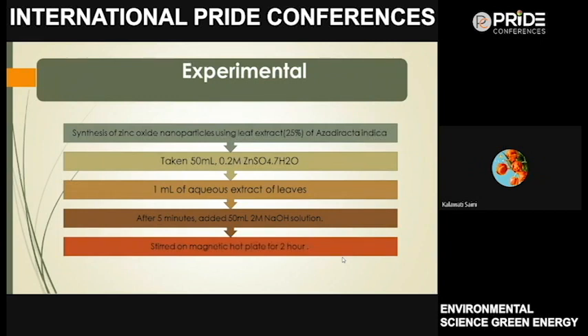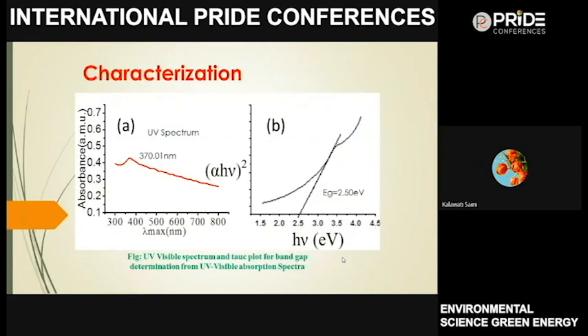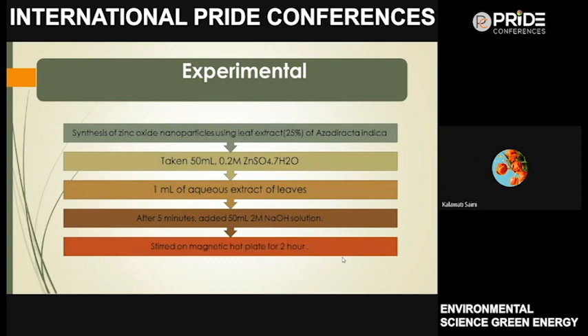We take the 25% aqueous extract of leaves of Azadirachta indica and take 50 ml of 0.2 molar zinc sulfate heptahydrate, and 1 ml aqueous extract of leaves, that is the 25%. After 5 minutes, we added 50 ml of 2 molar sodium hydroxide and stirred on a hot magnetic stirrer at 40 degrees centigrade for 2 hours. Then we get the white colored precipitate as well as particles in colloidal state.